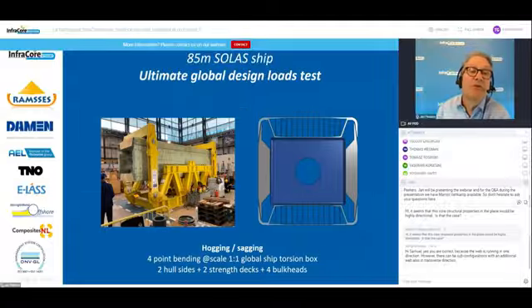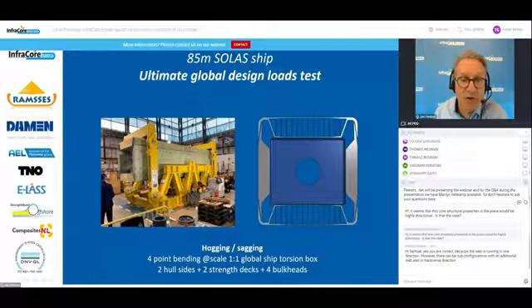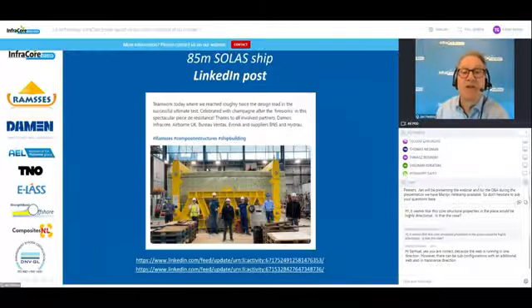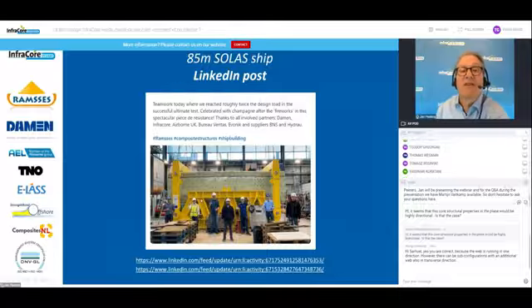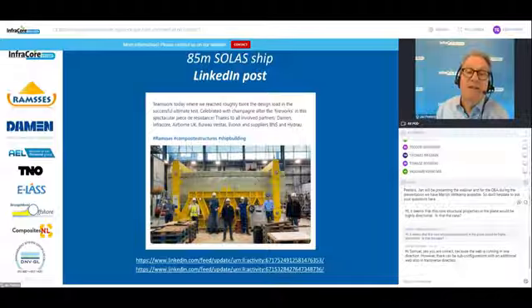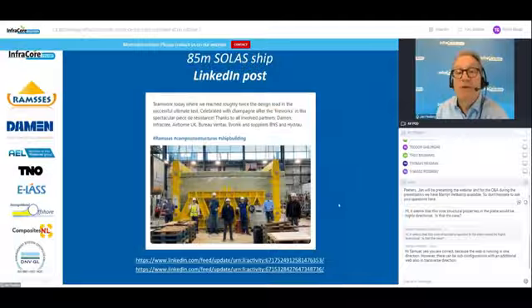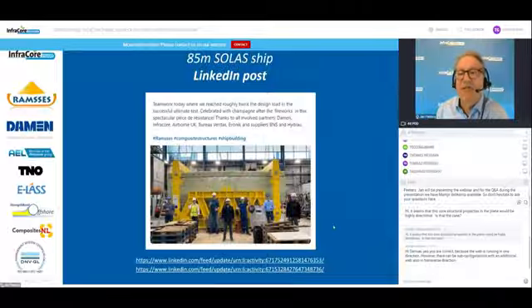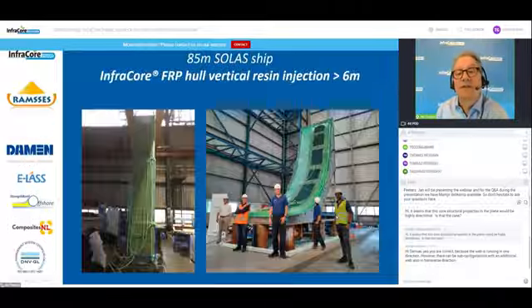One step up, the joints which have been developed are used in this application, which is a full-scale model of a ship. So the laminate, the deck thickness is realistic. The side panels represent the hull. These are realistic. The joints are scale 1:1. The bulkheads are scale 1:1. What you see here is a four-point load test where we try to break the ship. So this is simulation of hogging and sagging deformations. And the test has resulted in an 800-ton load, which was carried by this sample, which is an extreme load. And in this references, you can look at the films which are associated with that.